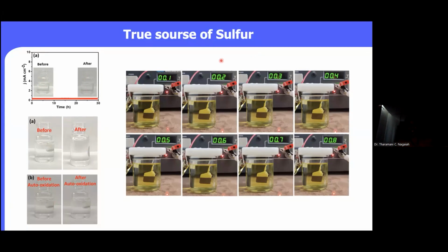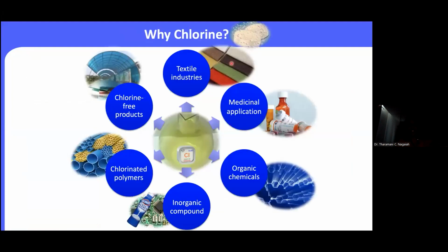And to understand again whether the activity is due to the catalyst or not, without the catalyst, we have performed some control experiments. And we saw that with an increase in the potential, we did not see any bubbles on the electrode. So that means this is not good enough to produce hydrogen even at 0.8 volts. So we need the catalyst to break this H2S into sulfur and to do this catalysis and also to produce the hydrogen. So now the other important topic is chlorine.